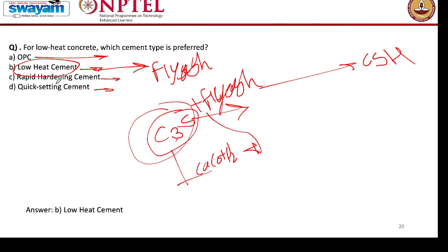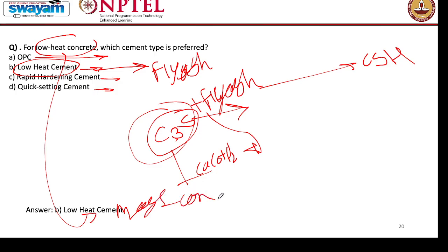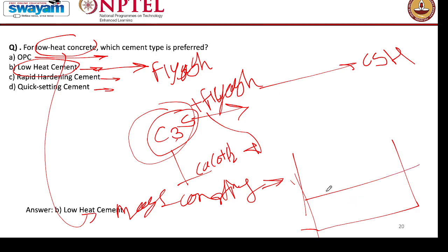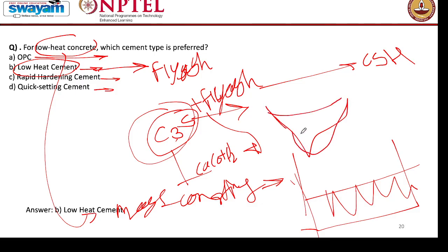Where there is a requirement of low heat concrete. Where is the requirement of low heat concrete? Applications like mass concrete. Mass concreting, where very big structures like rafts of buildings or maybe dams, right? So dams will have a very high volume of concrete. Because of that, it could generate thermal stresses which could lead to cracking. So to eliminate that, we go for using SCMs like fly ash, which reduces the heat of hydration in the early stage.